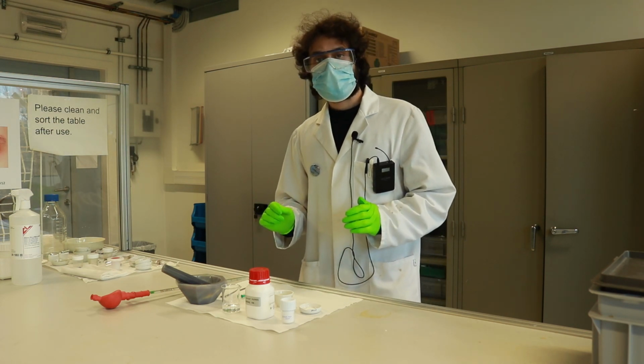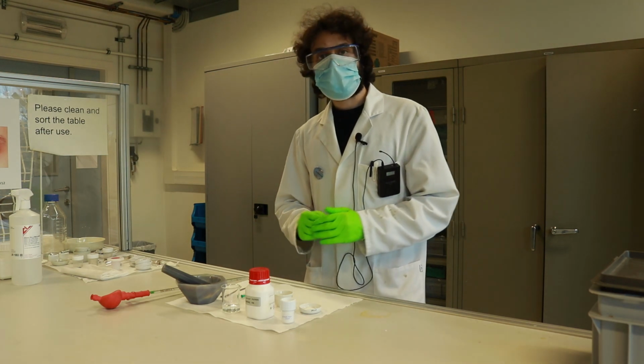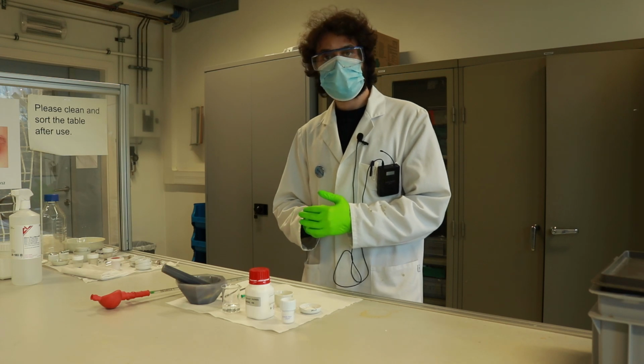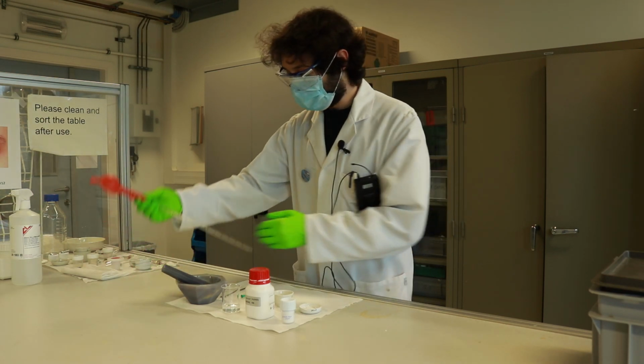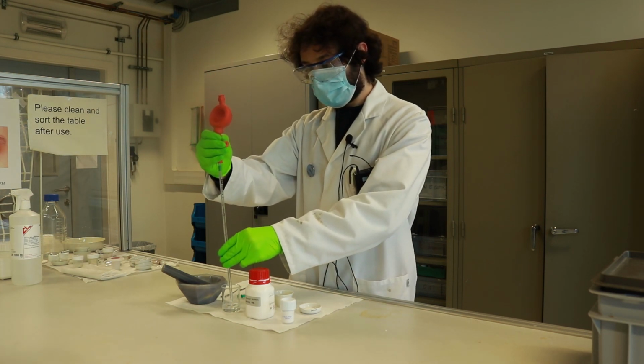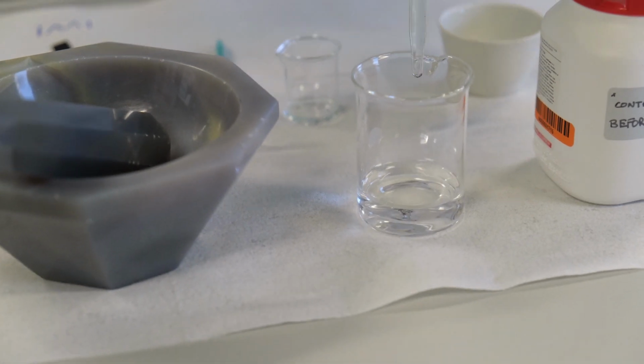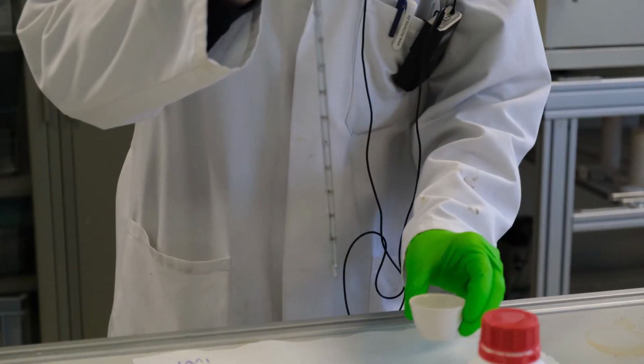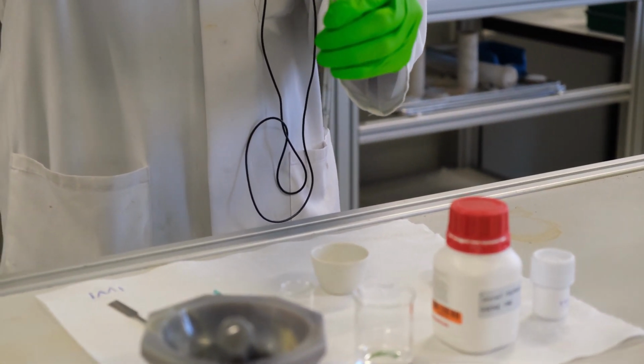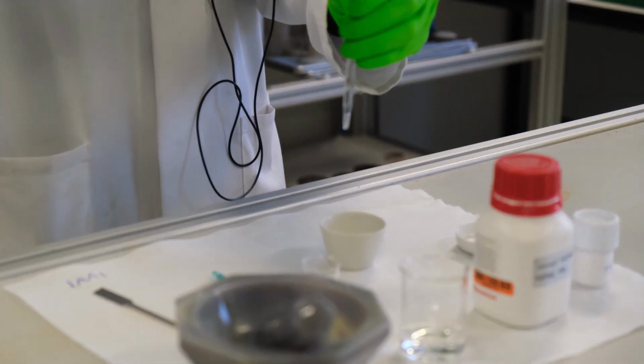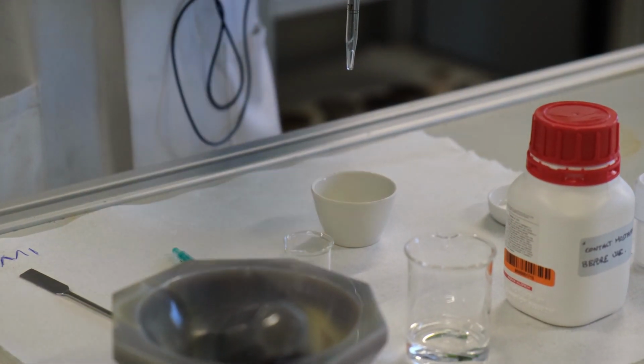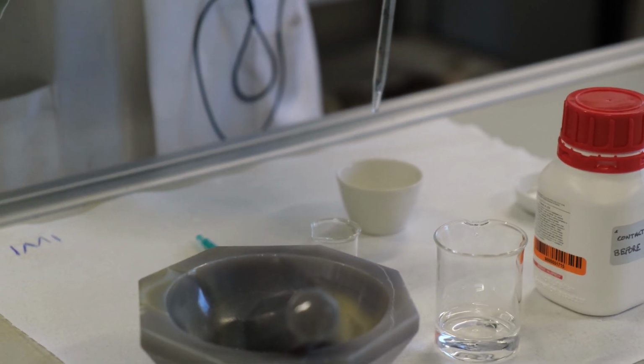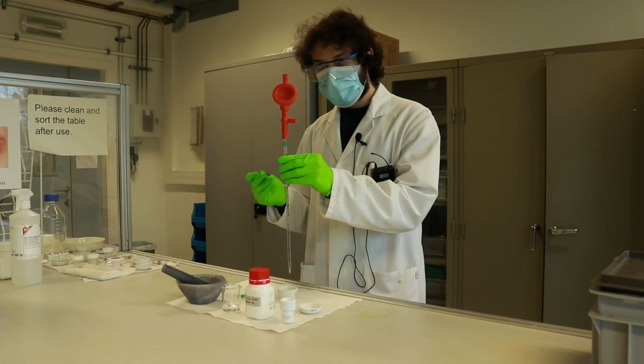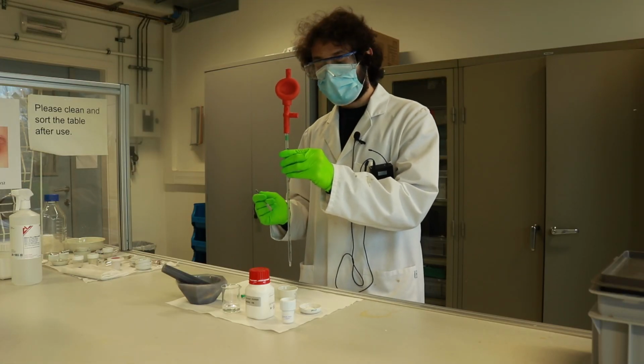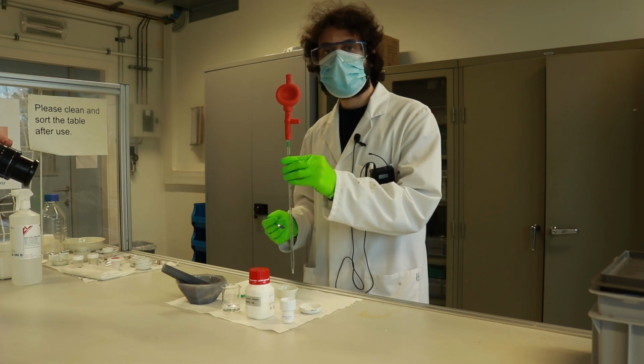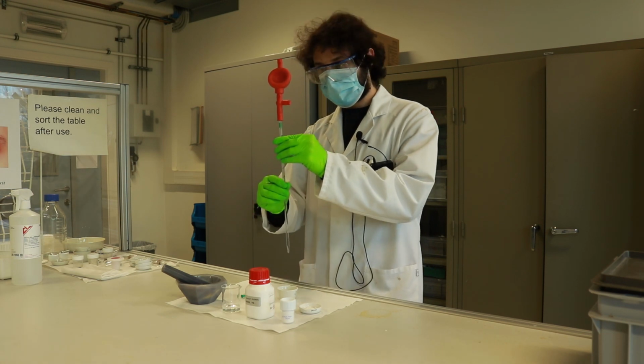So first things first, we will titrate the gamma alumina support with some deionized water in order to find out the pore volume. Over here I have a pipette. I have some deionized water. And I have a sample that I have pre-weighed before starting this. And so I will slowly start to add drops of deionized water while mixing the mixture, and I will only stop when the entire sample is wet. Remember, we do not want the sample to be suspended in water. We just want to fill the pores.